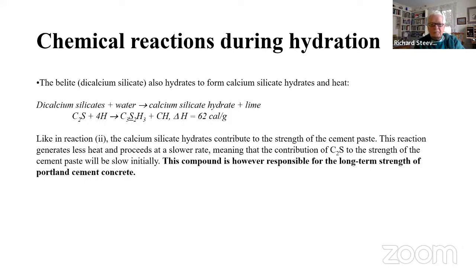So this dicalcium silicate also hydrates to form a calcium silicate hydrate and more heat. And it contributes to the strength of the cement paste. And it's interesting, I copied this out of documents online, and cement is always called a paste. I've never thought about it in those terms before, but that's one of the things that I learned as a result of this dive into concrete. This reaction proceeds at a slower rate, and so it develops its strength more slowly, but the compound itself is responsible for the long-term strength of the Portland cement concrete, and it does that by slowly curing over time.